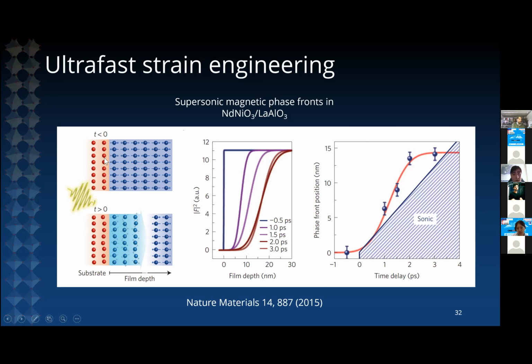So a magnetic phase front propagates from the interface into the film, and so through a resonant X-ray diffraction experiment, you can reconstruct the shape of your antiferromagnetic order parameter in the interior of your film, and you find that first the antiferromagnetic order is melted at the interface, and then this paramagnetic state propagates into your film at a speed that is faster than the speed of sound. So you have an order-disorder transition triggered by this lattice excitation.